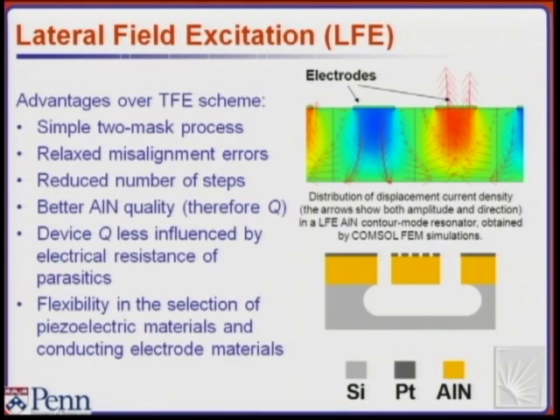There is a drawback that I'm not going to talk about too much, but when you use this type of configuration, now there has to be a specific ratio between the thickness of the film and the lateral dimension. So it sort of limits the frequency range that you can use. So you basically have H, where H is the thickness of the film, over lambda, which is the acoustic wavelength that you want to generate, which has to be about 0.5, the ratio of the two, in order to get maximum electromechanical coupling. So you're sort of limited in the range of frequency for a given thickness that you can achieve. You have a small spread of that curve.